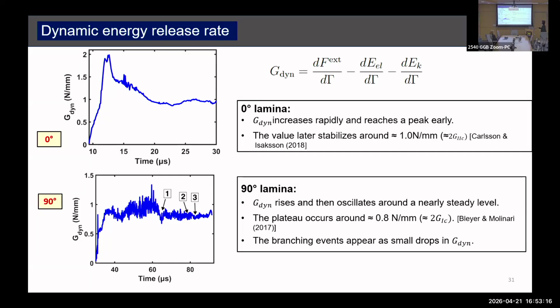And as I mentioned before, if you see, 0 degree spikes very quickly, comes down and then becomes stable. On the 90 degree, it was more oscillatory, much lower value. It doesn't gain as high as this one, but it was still showing some of this dip in the energy plot, which was corresponding to those branching events.